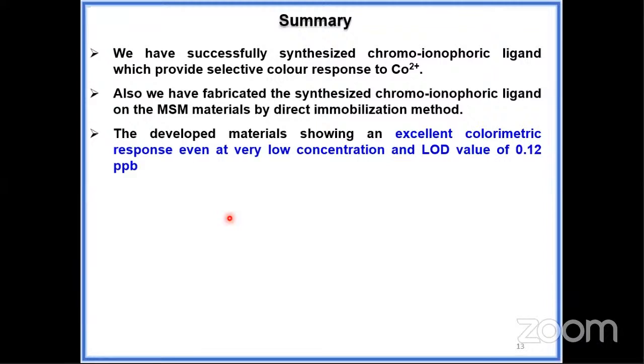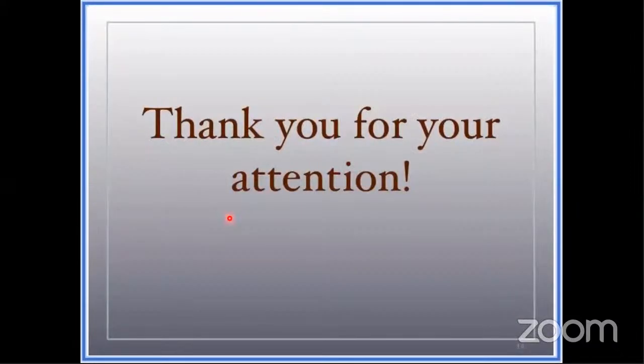Summary of the work: we have successfully synthesized a chromoionophoric ligand, which can provide an excellent selective response to cobalt metal ion alone. Also, we have fabricated the chromoionophoric ligand onto the mesoporous silica monolithic material by the direct immobilization method. The developed material shows an excellent colorimetric response even at very low concentration, with a limit of detection of 0.12 ppb. Thank you for your attention.